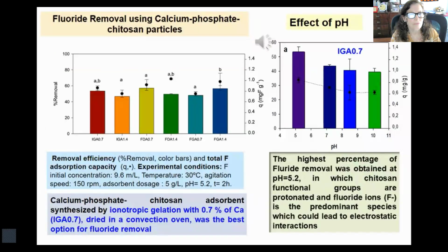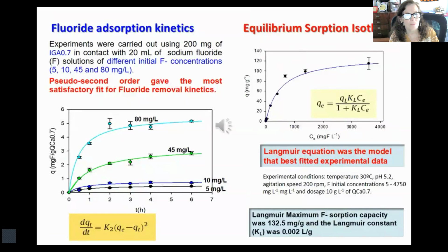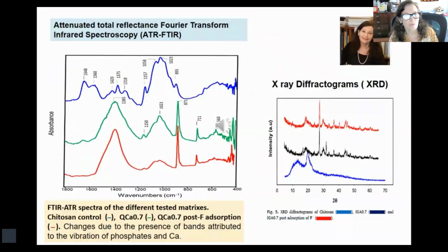Calcium phosphate chitosan adsorbent synthesized by ionotropic gelation and containing 0.7% of calcium was the best option for fluoride removal. Pseudo second order gave the most satisfactory fit for fluoride removal kinetics. On the other side, the Langmuir equation was the model that best fitted experimental data of equilibrium sorption isotherm. The particles were analyzed by infrared spectroscopy and X-ray diffractograms.